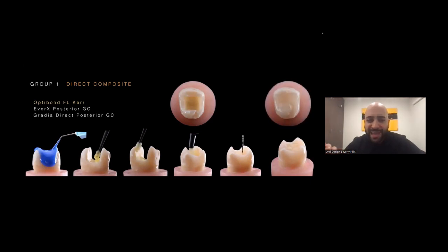In our first group in this study, we decided to do something different with our direct composite group. And that was using fiber reinforced composite from GC America, what we called EverX Posterior, as our dentin replacement. Now, our bonding protocol was here done with Optibond FL, and the composite we used really was just a normal, regular filled Gradia Direct composite. But what we were interested here to test with the direct group is how does this fiber reinforced composite affect this shrinkage that we've been looking at for years, and also the fatigue resistance and fatigue quality of the restorations.